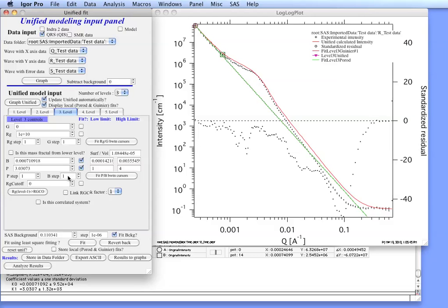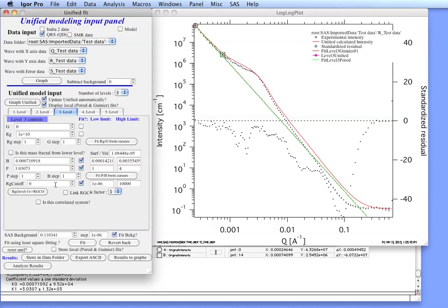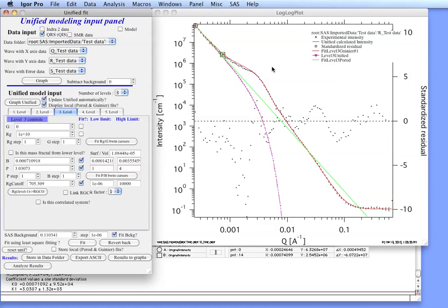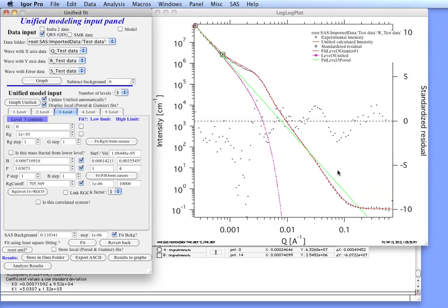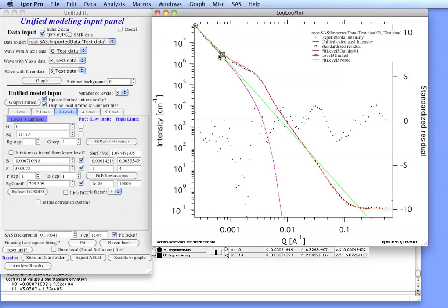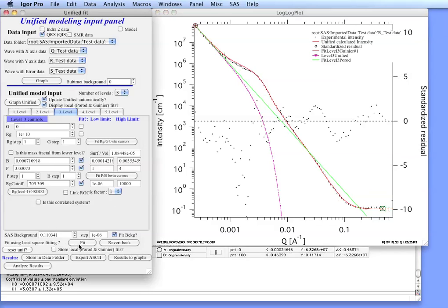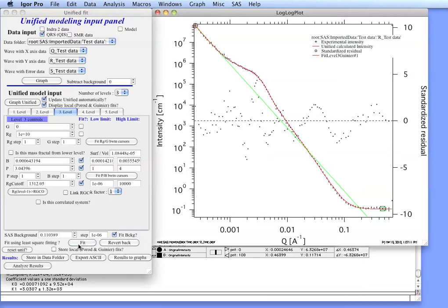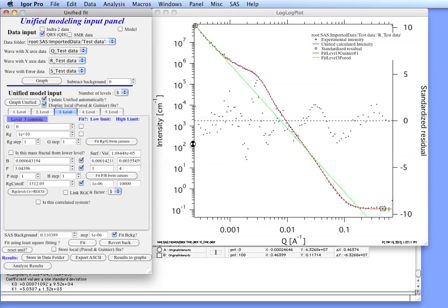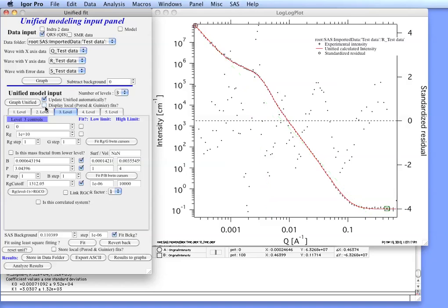This is solved in Unified Fit by terminating the small angle scattering from the higher level at the RG level of the lower level. And you can do it actually by either pushing this button here which copies level 2 RG into level 3 RG cutoff, or you can actually link them together with this little checkbox which is what we will do now, or you can just type in the number. If we do this you can see that the RG cutoff causes the scattering from the higher level to terminate and really fast disappear around the size around the RG of the lower level. In this case the predicted scattering from this level disappears much earlier and does not cross over the measured data. So with this we can now select all the data we have from the top to bottom and we can say fit. You can see that we have beautifully optimized the data. We can then uncheck this checkbox here and we have a very good fit with reasonable normalized residuals.